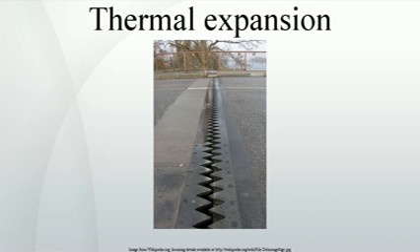Materials with anisotropic structures, such as crystals with less than cubic symmetry, and many composites, will generally have different linear expansion coefficients in different directions. As a result, the total volumetric expansion is distributed unequally among the three axes. If the crystal symmetry is monoclinic or triclinic, even the angles between these axes are subject to thermal changes. In such cases it is necessary to treat the coefficient of thermal expansion as a tensor with up to 6 independent elements. A good way to determine the elements of the tensor is to study the expansion by powder diffraction.